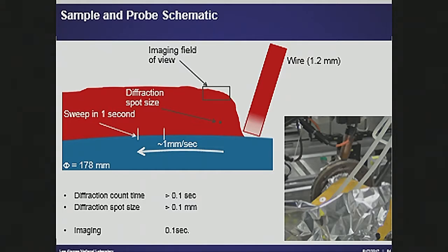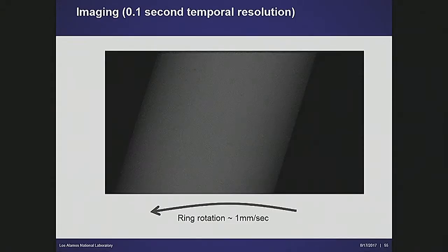Remember that the wheel is rotating by about 1 millimeter per second. Diffraction count time is about 1/10 of a second. Diffraction spot size was, I think, 0.1 or 0.2 millimeters, and then it was about 1/10 of a second for the imaging as well. So this